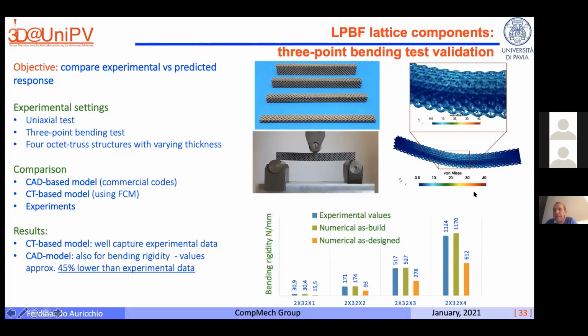Let's look just at these last results, for example. You can see here in this column the experimental value. In this other column, you can see the numerics obtained adopting as a base for the numerical simulation the idealized geometry. And as I was mentioning before, these results are much different than the experimental results. The two structures are completely different. But if you use the really produced geometry, so the CT scan based geometry, you get a very good match between numerics and experiment. So lattice structures can be really problematic, and advanced computational tools can be really effective.